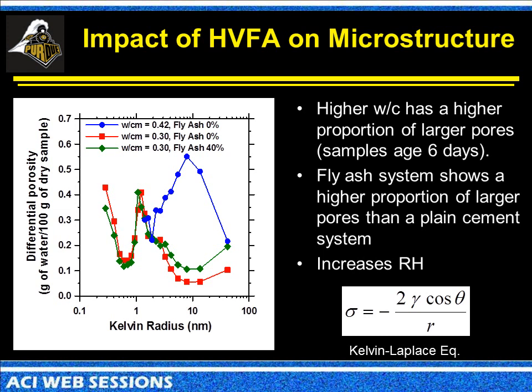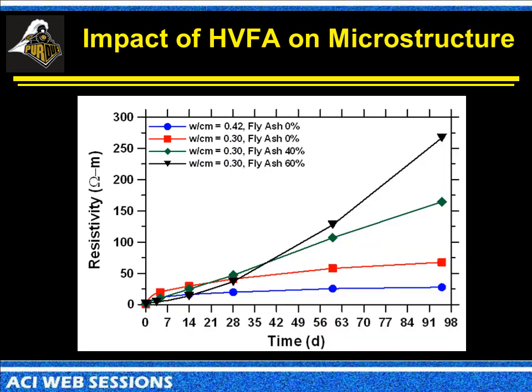So as I mentioned before, the stress that's going to develop that causes the shrinkage is going to be related to essentially the surface tension of water divided by the size of the pore. So we're really interested in, one, making sure that we know what sizes of pores we're dealing with in these higher performance materials, and the second thing is making sure that we keep them full of fluid so they're not drying out and not creating this high level of stress inside the system. I won't talk about this a lot, but one of the additional benefits that we're going to see when we start looking at higher volume fly ash mixes is the increased electrical resistivity, or the increased RCPT numbers. And here you can see a pretty dramatic difference.